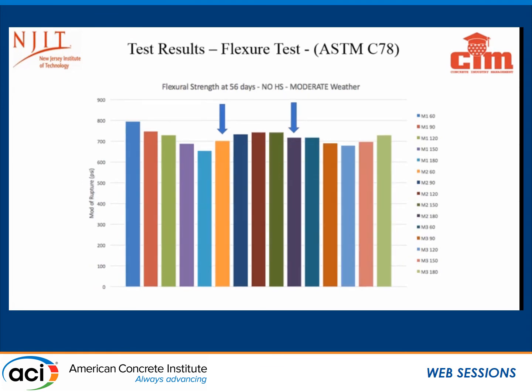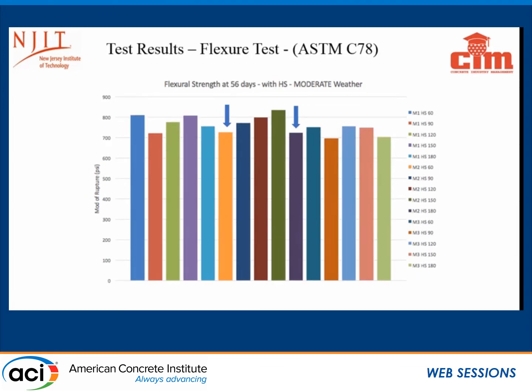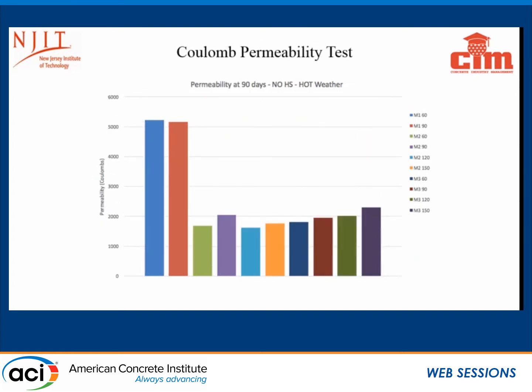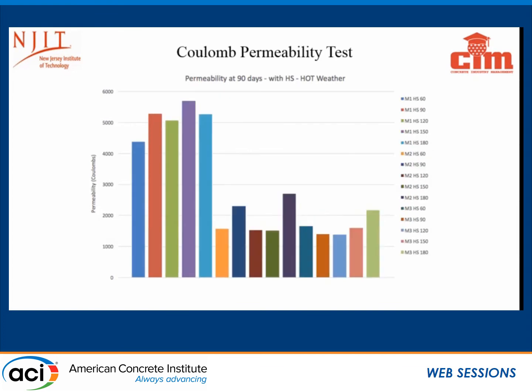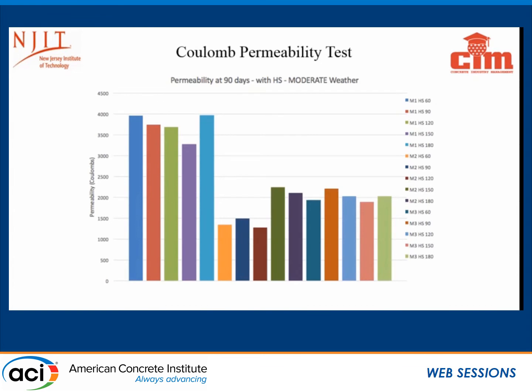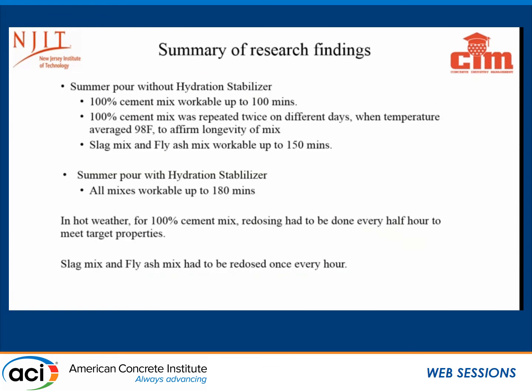Here we have the mixes showing flexural strength in moderate weather, no hydration stabilizer, and you have mix two between here. Again, flexural strength at 56 days with hydration stabilizer this time, and you see how fairly consistent it is. So the results are showing that there's no impaired effect on the concrete. You have your permeability test. As you can see, reduced permeability when you incorporate these supplemental cementitious materials. Same thing here, 90 days in hot weather with hydration stabilizer. You have the results between it. Again, fairly consistent. Okay, this one is 90 days in moderate weather with hydration stabilizer. So that was the last of the charts.